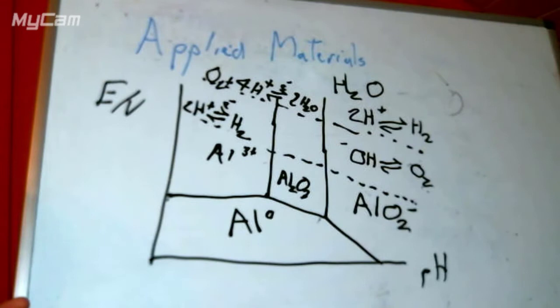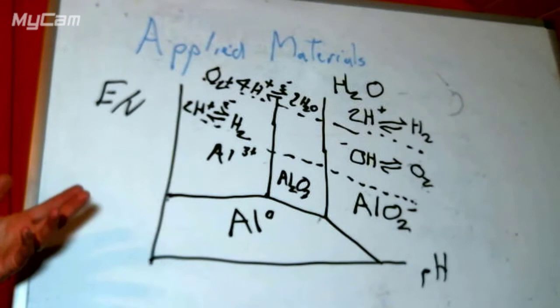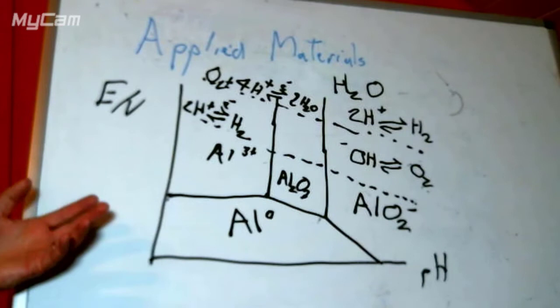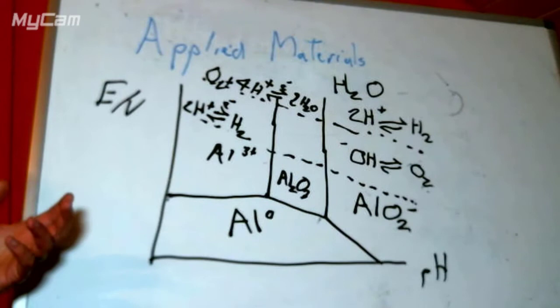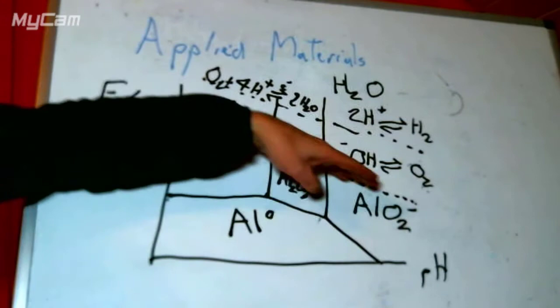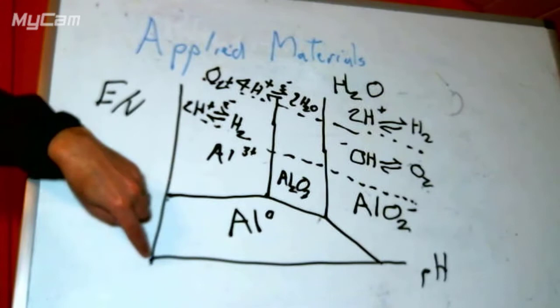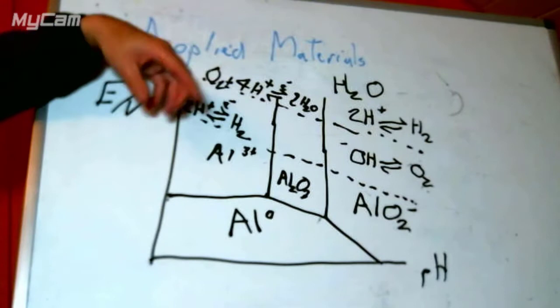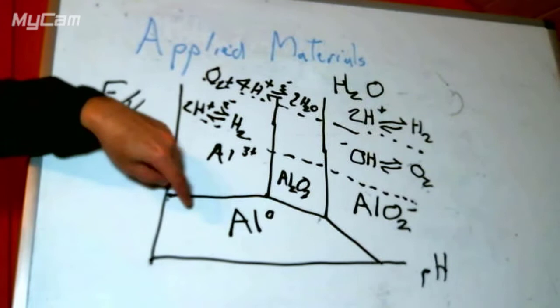As mentioned, aluminium is not thermodynamically stable in water — it will eventually react forming hydrogen and aluminium salts. The hydrogen line is at an angle because there are two H⁺ ions in the reaction — the more acidic it is, the easier that reaction is to happen. Over on the basic side, it becomes less likely for hydrogen to form, and so this line is at an angle. The oxygen line is similarly angled because we have H⁺ in that reaction too.